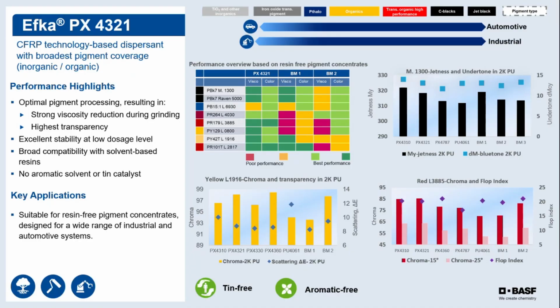And then in the same top row on the right, we look at carbon black, a high color carbon black. So this would be Monarch 1300. Two key aspects of carbon black that are important are jetness and undertone, and you want those to both be as high as possible. You can see 4321, which is the second from the left, is very competitive for jetness as well as undertone. And primarily it is beaten out by our Efka PX 4310, which is our industry benchmark for carbon blacks. But compared to all the other benchmarks, it more than holds its own.